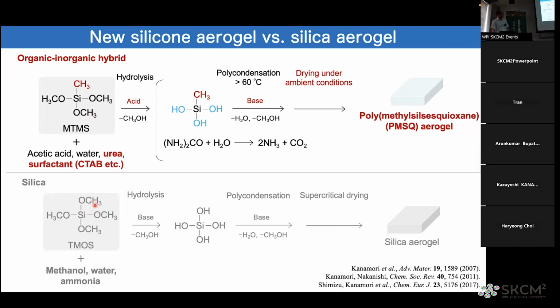The chemical process of this precursor is a little bit complicated compared to that of silica aerogels. In the case of silica aerogels, it is easy to obtain the wet gel by dissolving the precursor in methanol and basic water. Then the reaction goes to form the gel, a beautiful gel. It's very easy. Then you need to dry the gel by a supercritical process. But in our process, the precursor forms a hydrophobic network in aqueous solution. So we have to prevent the phase separation in aqueous solution. I won't go into detail, but we use an acid-base two-step process to promote monolithic gelation. And we also use a surfactant to suppress the phase separation. After forming the gel, we can obtain the aerogel by ambient pressure drying.